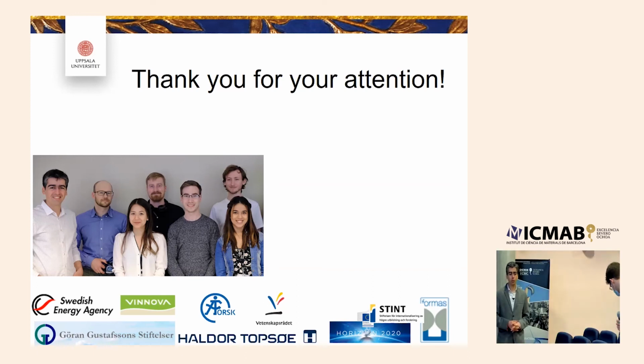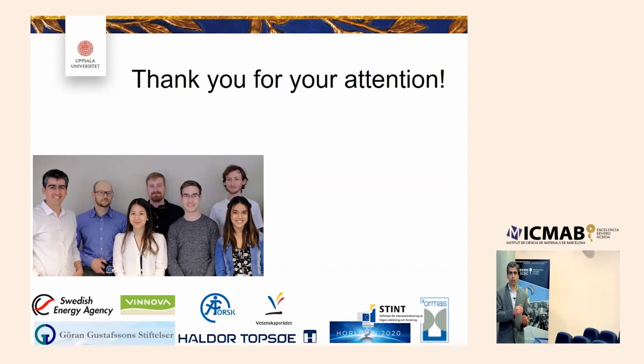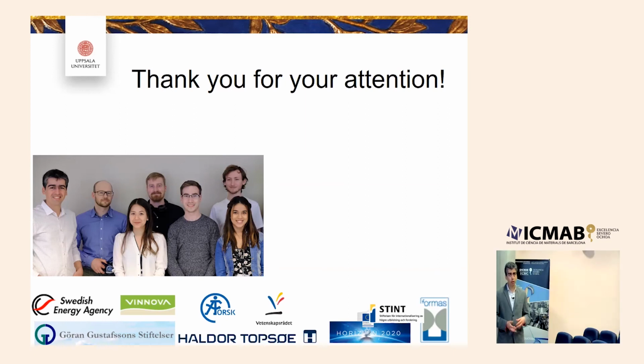You are right. When we did ICP to measure solubility, this was in solvent only, because otherwise it would be extremely difficult to measure solubility of lithium fluoride in a real electrolyte. But when we did electrochemistry, where you could see a clear connection between solubility, capacity loss, and volume, everything was real electrolyte, 1 molar sodium PF6. When we did mass spec, these were real electrolytes coming from cells, so there was 1 molar PF6. That's why it's also very difficult to assign the peaks to a specific compound; we had to just trust the differences we see between the different peaks.